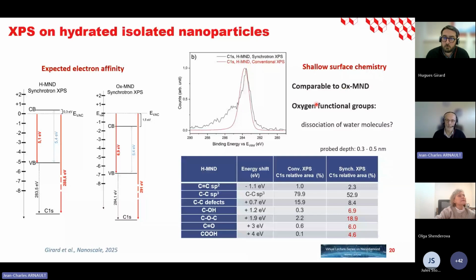So the point is, why do we have these oxygen functional groups? For the moment, the hypothesis we have, but we have to prove it more, is that it could be related to a dissociation of water molecules on the hydrogenated surface of the MND particle. This phenomenon has been seen for hydrogenated bulk diamond before by Alon Hoffman's group.